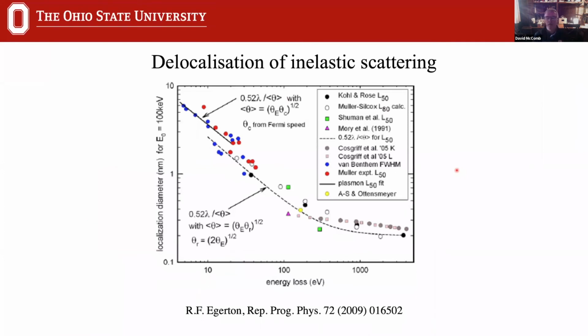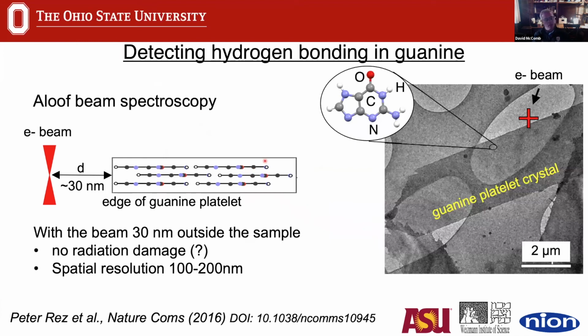In the early days of looking at phonons using EELS, many of us assumed that this would be limited to relatively low spatial resolution, because it's well established that as we go down in energy loss, the localization diameter increases because of the long range interaction of these low energy excitations. So this goes down to 1 electron volt. So you can imagine that if we were to take this down on our log scale to 100 millielectron volts, then we should have a delocalization length scale that's maybe of the order of 30, 40, even greater nanometers. So we really thought this would be the case, but it's still very powerful.